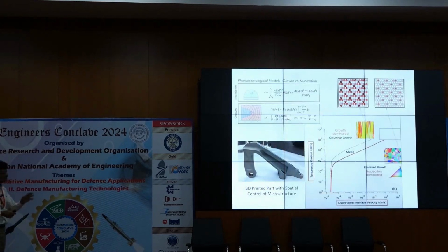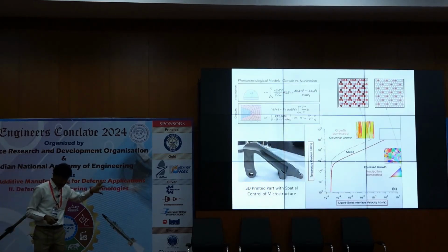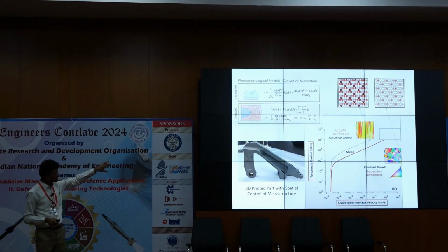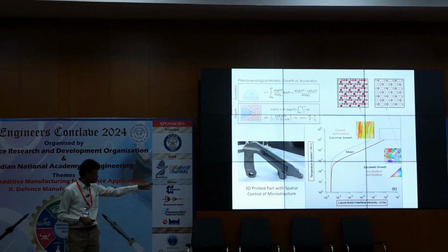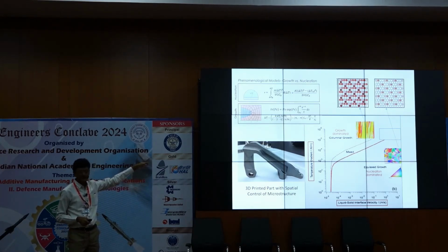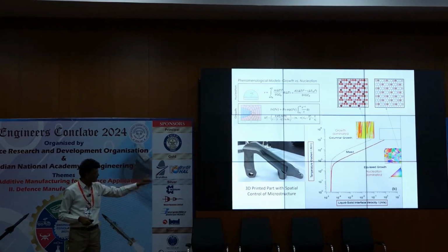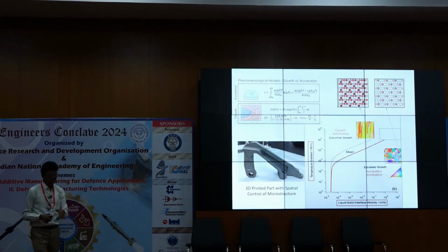And in these cases, the entire approach can be based on the phenomenological models connected with the growth and nucleation. And you can quickly infer that in the zones where you have a low liquid-solid interface velocity with a high temperature gradient, you can get a columnar structure. At the other extreme, you get that equiaxed growth structure. So where does it lead to?